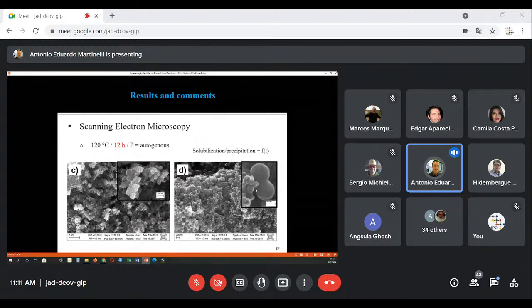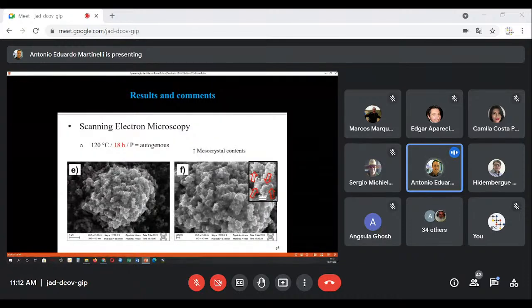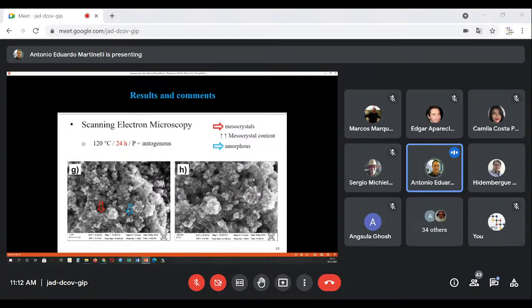here now the solubilization precipitation oriented aggregation of the powders. This is one of the growth mechanisms we're going to discuss in a few minutes. At 18 hours, we see the increasing mesocrystals. It's nice when you can actually, it's not possible to do it here. We should have done it as a movie, as a film. It's very nice when you see the time increasing for the same temperature and then the temperature increase and you see the change in the morphology and size of the crystals that are formed. Here we are at 24 hours. We still have organic material, we still have amorphous phase, but the content of mesocrystals now is much higher.